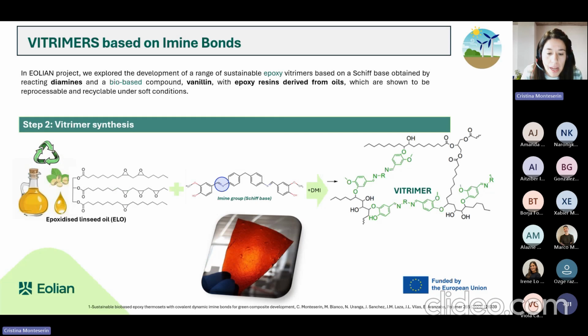In the second step, the hardener is reacted with an epoxy compound to obtain the vitrimer. In this case, epoxy resins derived from oils, such as linseed oil, have been selected as a renewable source.